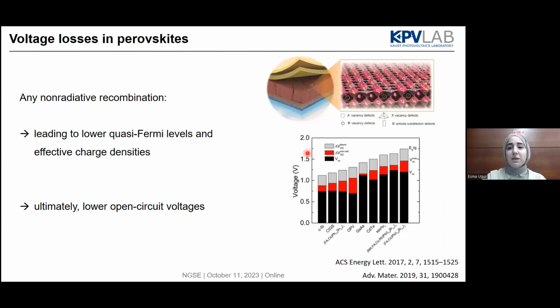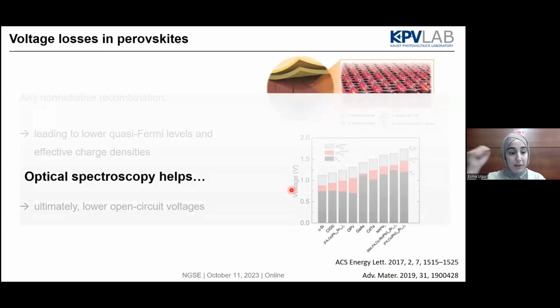But if we have some trap states, the generated carriers will be trapped, which leads to non-radiative recombination that we don't want in solar cells. Basically, it lowers the quasi-Fermi levels and reduces the effective charge densities. Therefore, you are lowering the open circuit voltage of the device in the end. But how can we probe these losses, or deal with the voltage losses? This is where optical spectroscopy comes in, and it helps a lot.